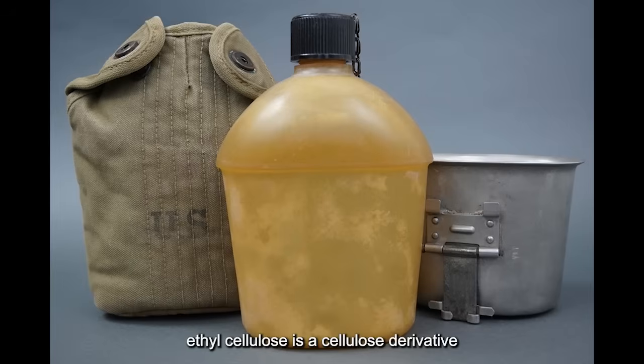Ethyl cellulose is a cellulose derivative where ethoxy groups replace hydroxyl groups on the cellulose polymer chain. When properly formulated with plasticizers and stabilizers, it can be relatively inert for short-term industrial uses. But the wartime Ethocel formulation wasn't stable enough for prolonged contact with drinking water, especially under heat stress. The American Ethocel was pure polymer, no filler, no protective barrier. The plastic contained residual solvents and plasticizers from the manufacturing process that hadn't fully evaporated or cured. When water filled the canteen, these chemicals began migrating into the liquid. Heat accelerated the process exponentially.